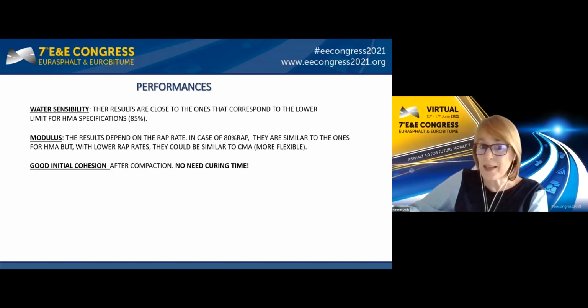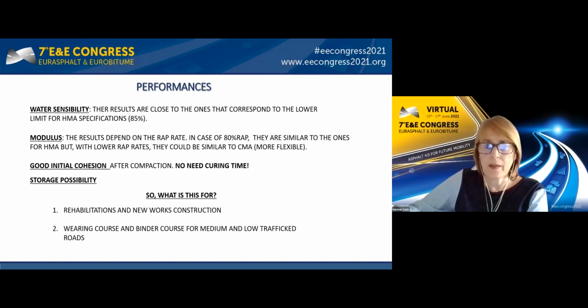We have a very good initial cohesion after compaction, so we do not need curing time, and we have the possibility to stockpile the mix and lay it 24 hours after. So what is this good for? Of course, I think it's good for rehabilitation and new works construction, but also for wearing courses and binder courses for medium and low trafficked roads.